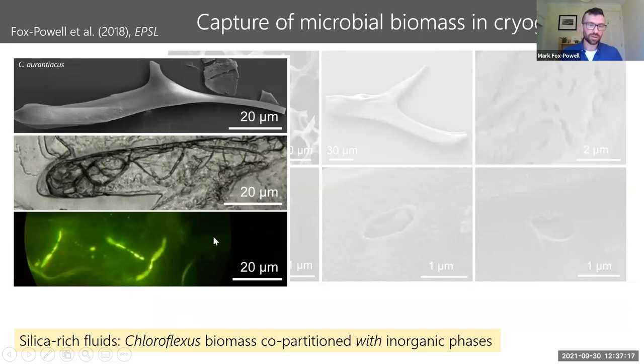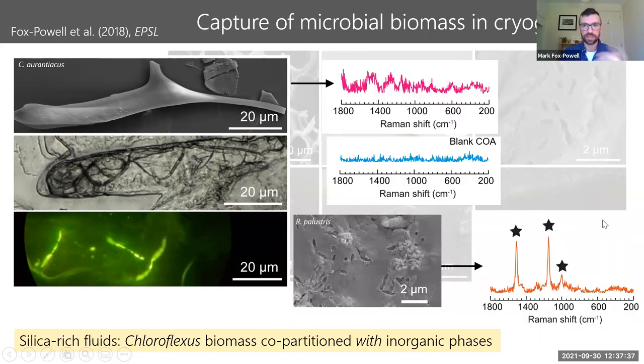Some strains, for example this Chloroflexus filamentous bacterium, were actually never observed on the surface of particles and were always encased within particles. So that's implying that this is co-precipitating with, or perhaps nucleating the precipitation of, this opaline silica. And that's corroborated by some spectroscopy we did, showing how pigmented microbes on the surface were very easily observed with Raman, whereas these Chloroflexus, also pigmented, were not observed by Raman, despite the fact that this is a surface technique, so it's really only probing the surface of these particles. We had Raman spectra that looked very similar to the experimental blank that had no biomass in it.